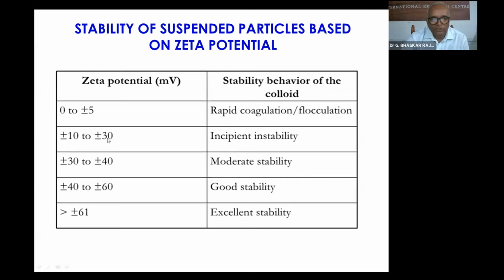And then 10 to 30 millivolts is incipient instability. Just slightly, it will become unstable. At 30 to 40 millivolts, moderate stability. Then 40 to 60, good stability. And above 60 millivolts, there is excellent stability. When the charge is very high on the surface of the particles, they get properly dispersed, so you have fine stability of dispersed particles in the liquid medium.